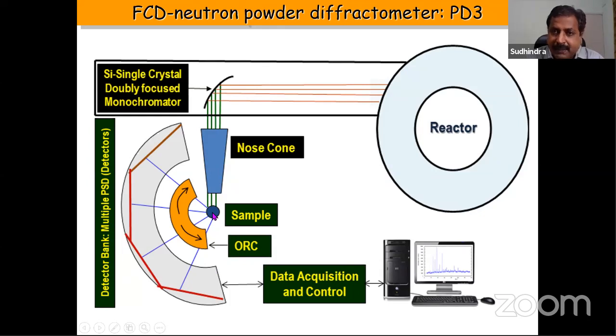As I said, we are also using some sample environment, which falls into the neutron beam line. Whatever comes in the neutron beam path gets scattered. To cut down the contribution from the sample environment, we use an oscillating radial collimator called ORC, which oscillates in the entire 2 theta range to cut out the background which comes from the sample environment. After the background is cut, the signal from the detector is fed to the data acquisition control system, which controls the experiment as well as records the data in intensity versus 2 theta format, which is further processed for analysis.